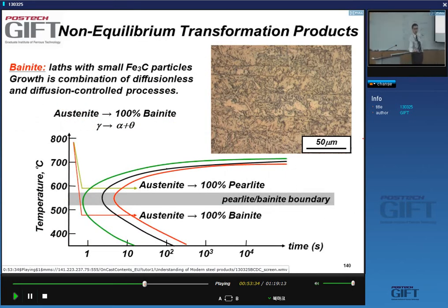Okay. Now, you remember that I told you around 550 something happens to substitutional solutes. In particular, they just stop diffusion. The diffusion of solute is pretty much finished. And below that, you only get interstitial diffusion, so carbon and nitrogen can still diffuse, but not the other atoms. And so when they do move, they do this by shear transformation, I should say, not shear deformation.